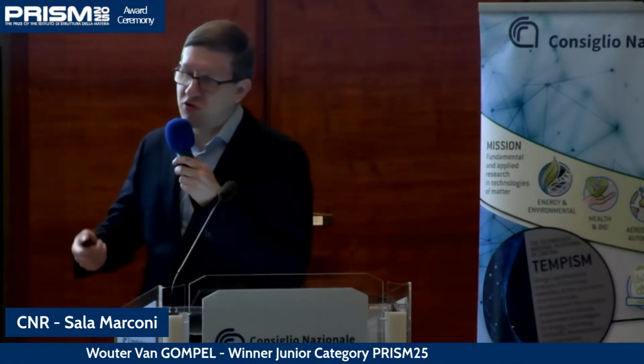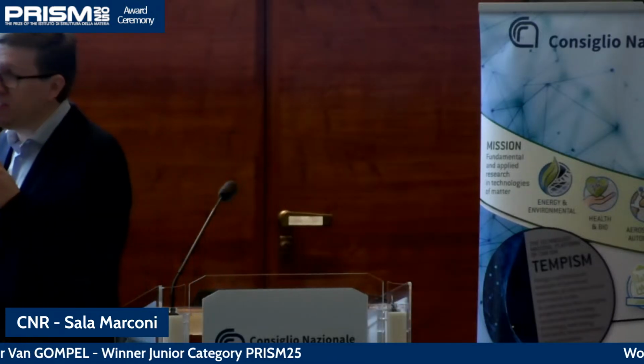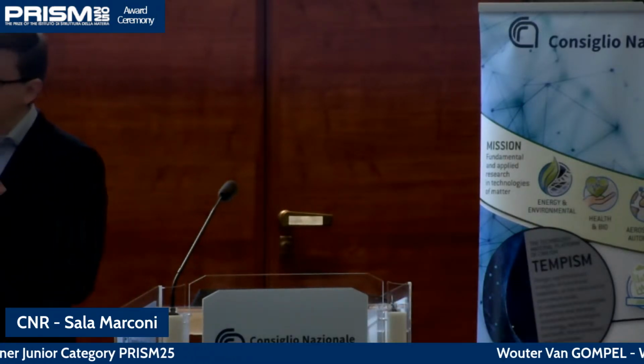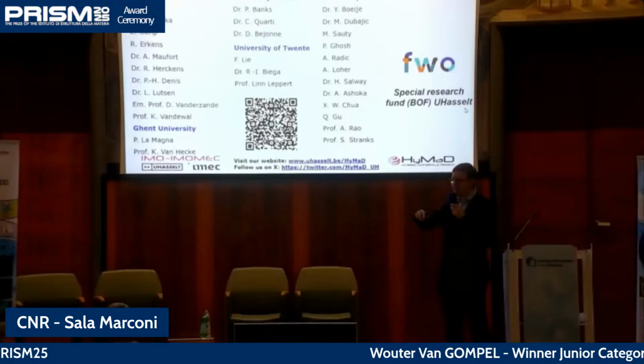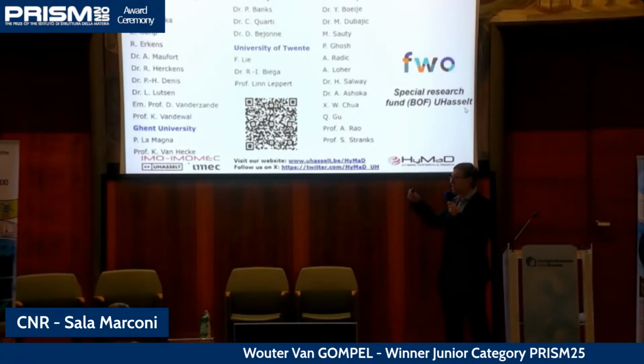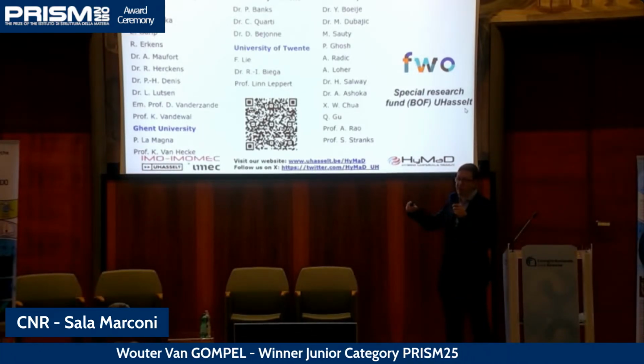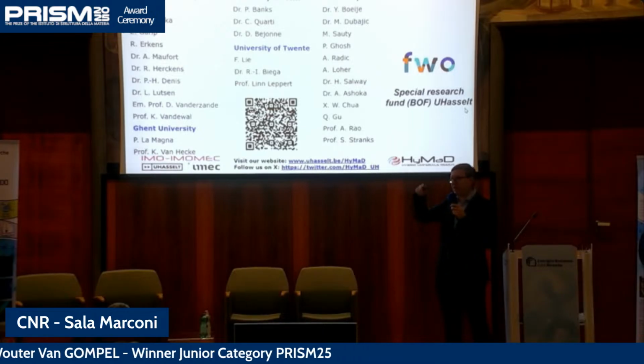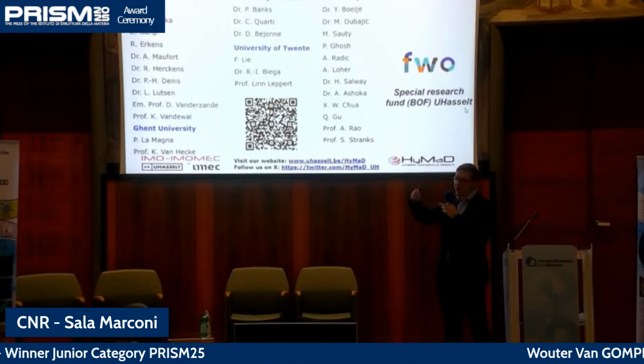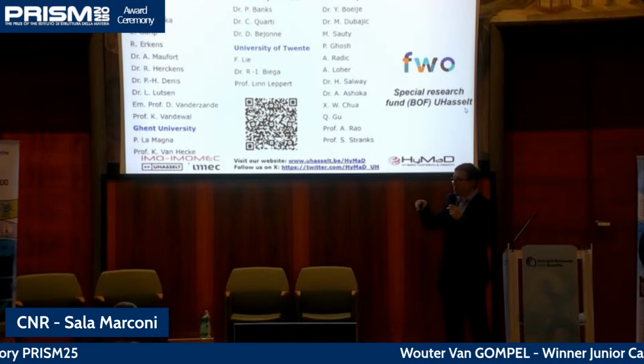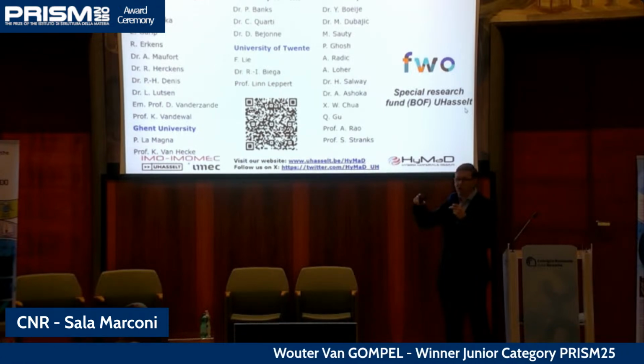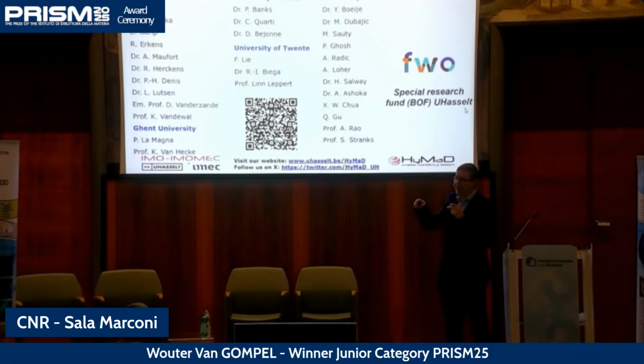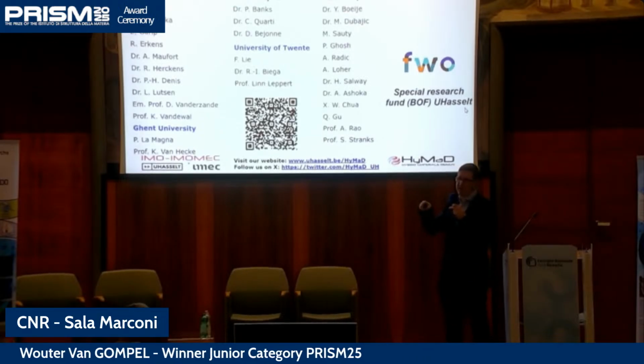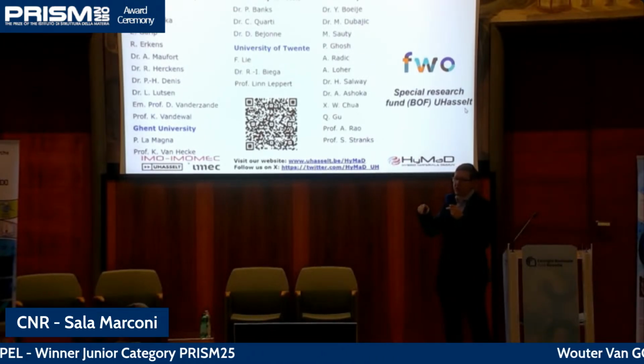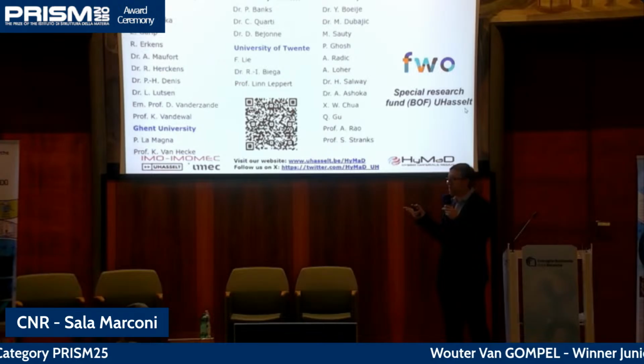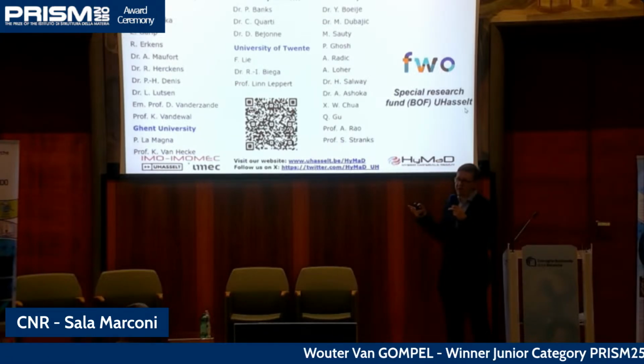Yes, indeed. So that's a completely valid argument. Indeed, if you would have a perfectly horizontal crystal, let's say, you would expect that the fact that you separate these charges hinders the charge transport in a device with electrodes on top and at the bottom. That's completely true. But of course, you have in a thin film crystallites of all different orientations, and then in a combined fashion, it still generates more charges than in the fully confined system, where you have, of course, this very high exciton binding energy of 400 meV even.